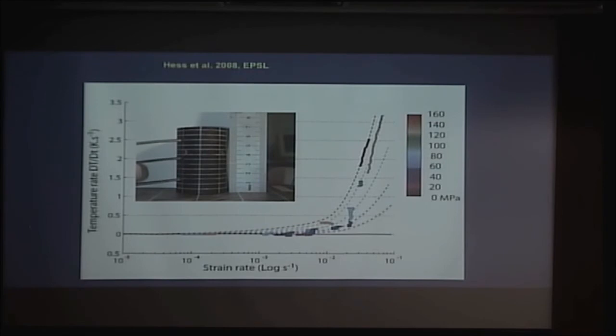And because the rheology depends on the temperature, we can actually indirectly calculate whether the temperature rise is consistent with the drop in viscosity that we see. And they match beautifully. So not easy to do at 500 degrees Celsius where you have an interactive temperature control in your device, but you can actually determine the onset.